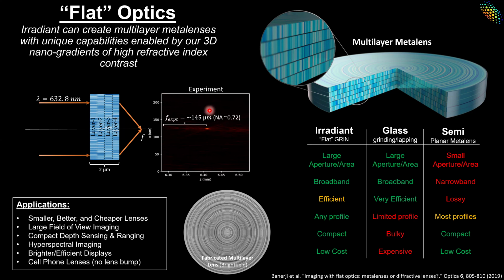So when you're making just one or even two planar structures, it's like trying to make a fully aberration corrected objective with just two lenses. But in our case, we can do fully arbitrary 3D optics, so we can stack as many lenses as we want to correct for a lot of different aberrations. This is an example of a 4-layer optic that we've made. It's about 300 microns in diameter, has a focal length of about 145 microns, so an NA of about 0.7, and is about 2 microns thick, corresponding to these 4 layers.